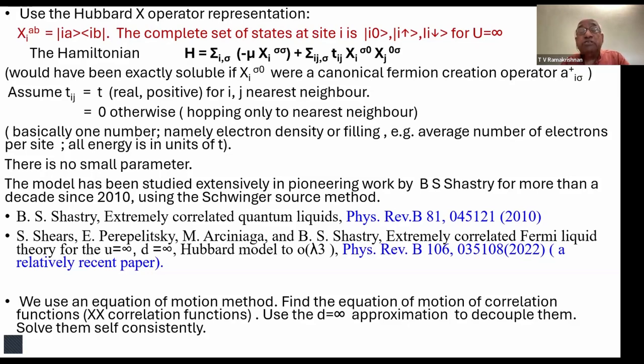We simplify this even further. We say that the hopping is non-zero between one site and another only if these are nearest neighbor sites. This is simply because hopping is via the overlap of quantum mechanical wave functions, and the wave function overlap becomes rapidly very small as distance increases, and therefore the only essentially non-zero, unavoidably non-zero overlap which has to be included is between nearest neighbors. So this model is characterized by 1 energy parameter, actually 2 energy parameters, but this energy parameter is basically related to the occupation number. Now, as I said, there is no small parameter in this theory. There is no perturbative expansion.